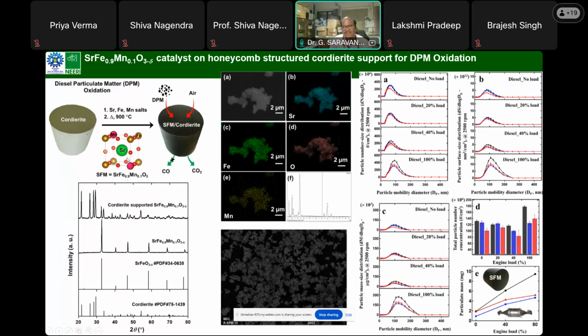So we checked this performance, and coming to the direct results, the blue one is a typical commercial platinum automobile exhaust catalyst. People are using it. When we coat this material on the typical cordierite substrate, the activity is almost comparable. The commercial catalyst has platinum, here there is no platinum. So that is the beauty of this work. At higher engine load, the catalytic activity is almost comparable with the commercial platinum catalyst. That is the important result that we found, and this work got patented.